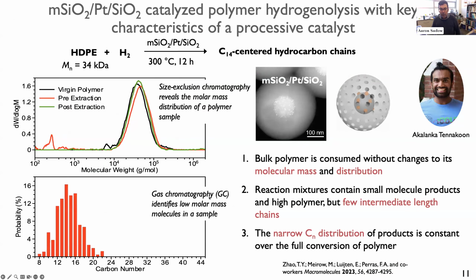Okay, so we envision that this might be able to be accomplished with inorganic catalysts and pores. And another colleague of mine, Wenyu Huang, pointed out that he had made these materials that are shown here. So this is a solid silica core, where Wenyu and his group have deposited platinum nanoparticles on that core, and then they grow mesoporous silica as a shell over top the material. So in cartoon form, it's here. You see the solid core, the little orange balls should be the active platinum sites, and then you have mesoporous silica. And the question was, would this kind of catalyst work in that processive fashion in a hydrogenolysis process?